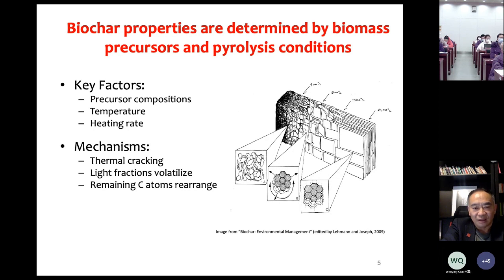Okay, and at lower temperature, let's say lower than 800 degrees C, there will be major change in terms of chemical composition, and the carbon content will increase. So the materials we are dealing with here, we produce at a temperature higher than 800 degrees C. As a result of that, they are highly carbonized, meaning that they have carbon content over 90%.